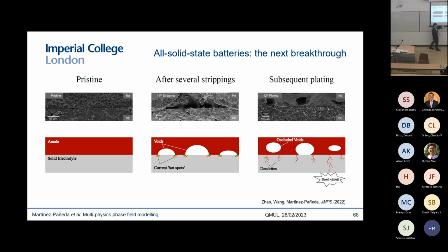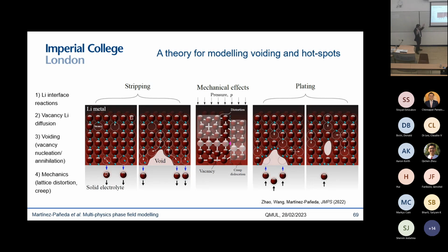Once you nucleate a dendrite, it's very difficult to stop it. So we're trying to focus our efforts on understanding under which conditions you form those dendrites. And for that, it is essential that we understand this voiding process. So we developed a theoretical and computational model to understand this. And this model has multiple ingredients. One is, of course, the interface reaction.